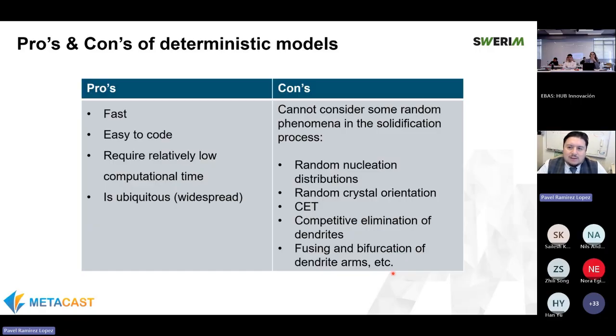And this randomness we miss in these deterministic models. We will get a distribution, but very often we will end up predicting the same shape. For example, if we are modeling a snowflake, we will end up predicting the same shape, whereas the reality is that we will always have some random nucleation events. The same happens with the crystal orientation. It will be random. The columnar to equiaxed transition will be difficult to predict. Now, there are ways to do it in deterministic models also, but in general, it will be more difficult.